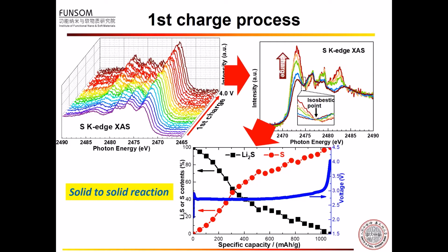Yeah. So in natural sulfides, it's pretty typical as you go from crystalline sulfides to something in solution, let's call it electrolyte, that you would go through polysulfide. So the fact that you see polysulfide as an intermediate suggests to me that you've got maybe some higher crystalline order in your Li2S. So it's interesting to know what that is. Okay, yeah, that would be interesting. But I discussed the data with some other people, because for the XAS, it takes around 15 minutes for one spectrum. In addition, for the conversion, the lithium polysulfide is very complex. It's maybe mainly the issue of the time scale, how fast it converts from one to another. Okay. Yeah, it's very nice. Very interesting. Thank you.